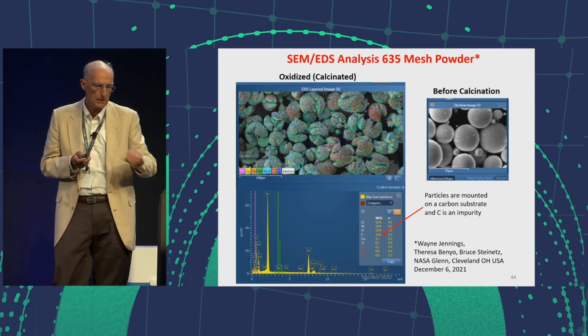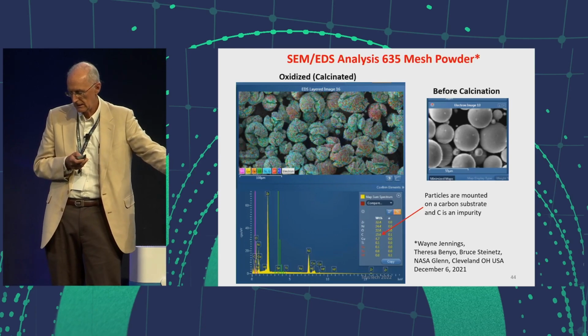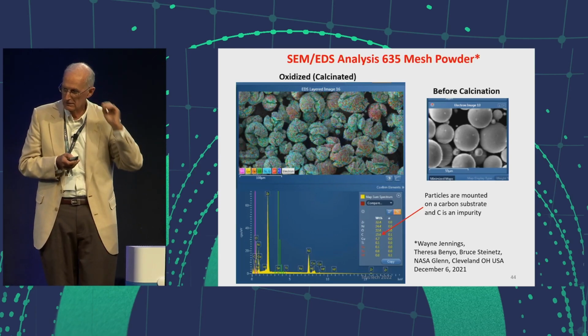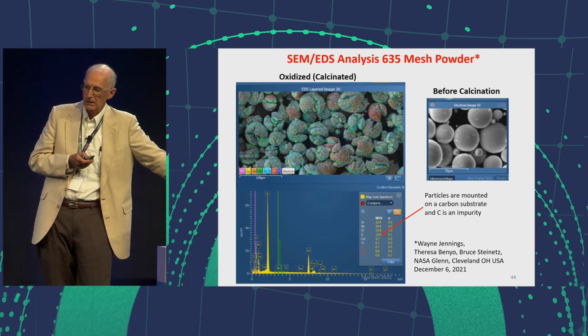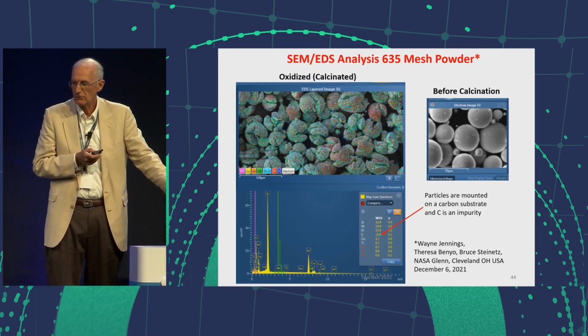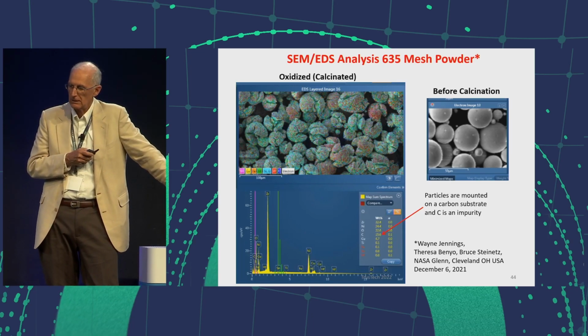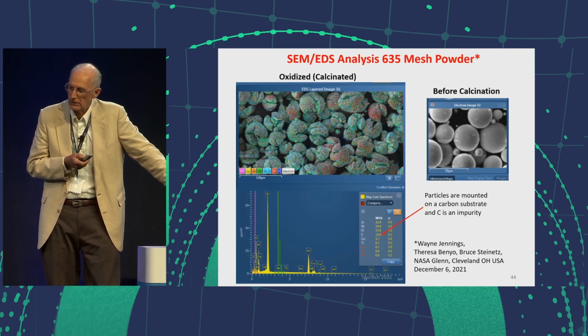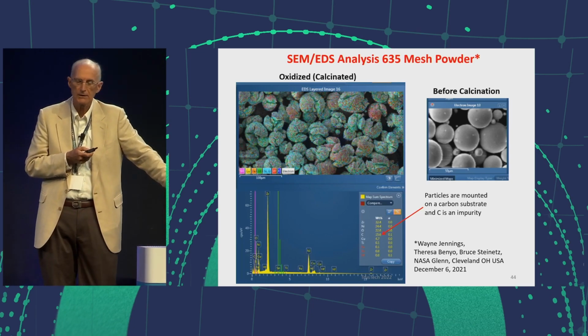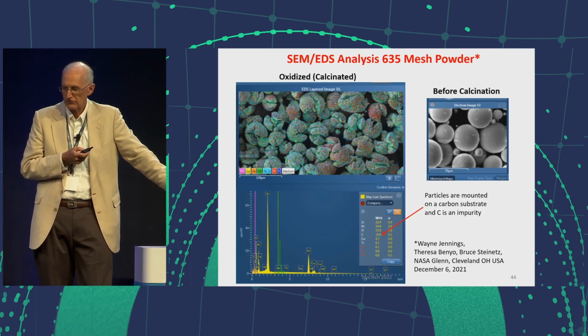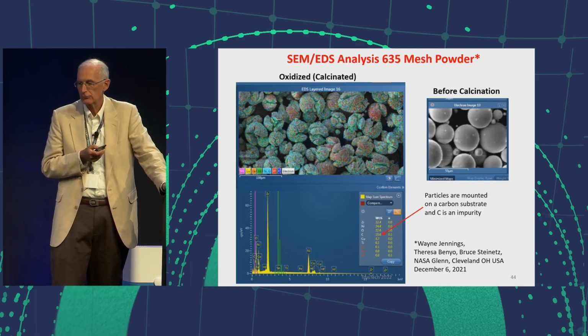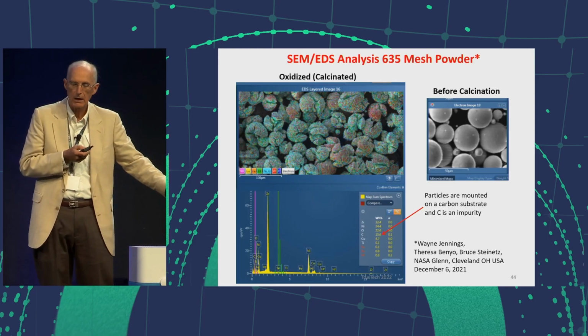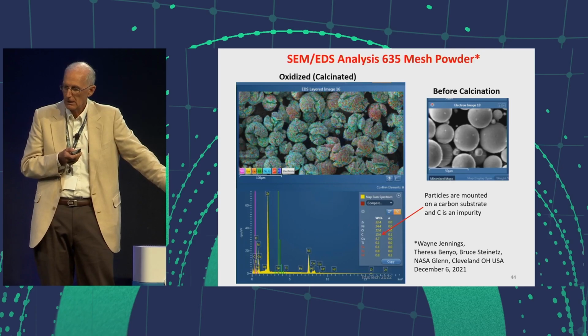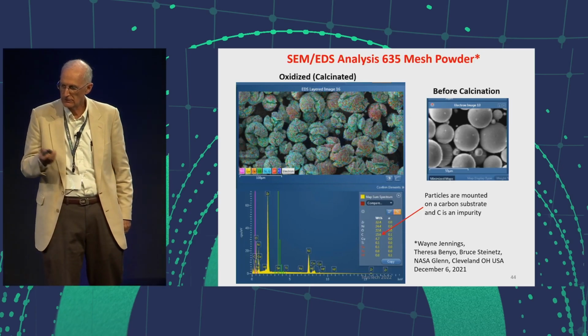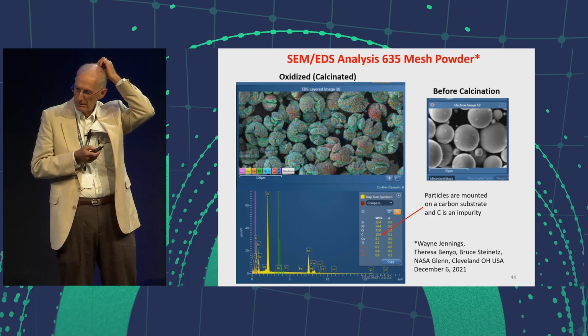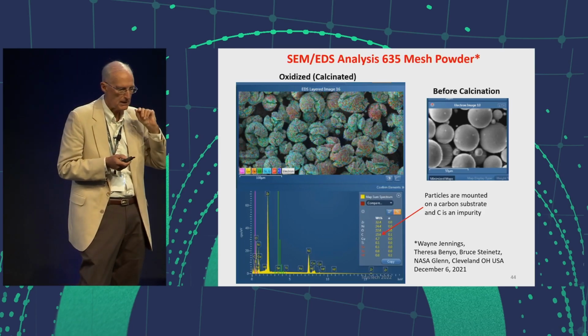Recently, I was able to renew a collaboration with NASA Glenn, and they were able to do SEM/EDS analysis of the particles. You can look at these at your leisure, but the right side shows the before picture of the particles before they were calcinated in the oven for a week, and the left side shows broken up particles with inhomogeneous spread of zirconium and oxygen on the outside. These were done by Wayne Jennings and under the direction of Theresa Benyo and Bruce Steinetz, who I've known for about 10 years.